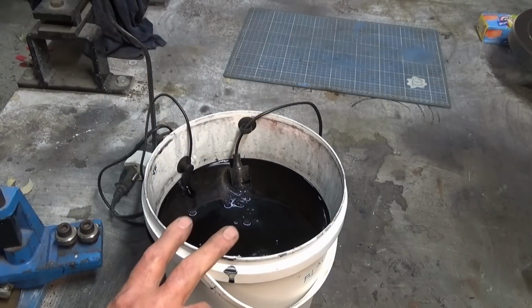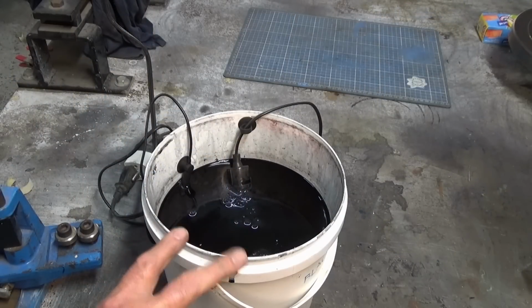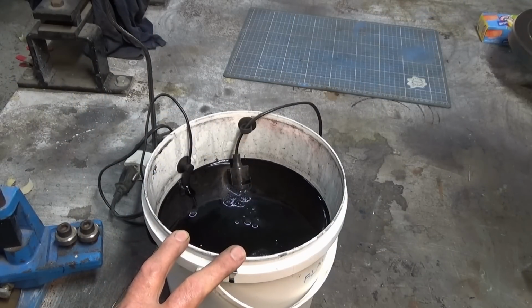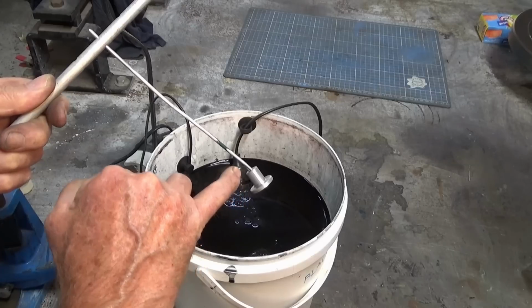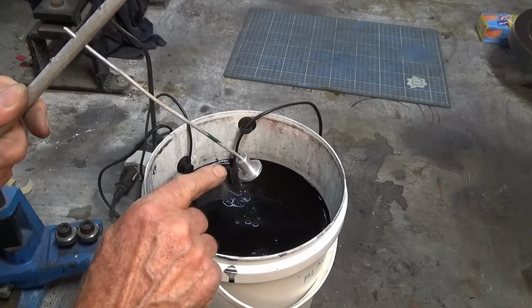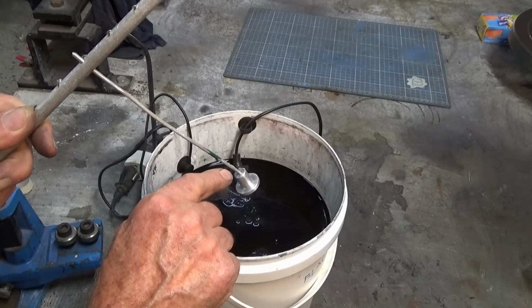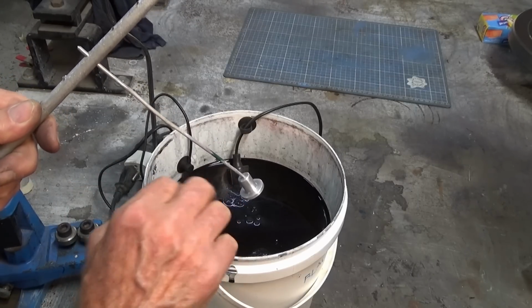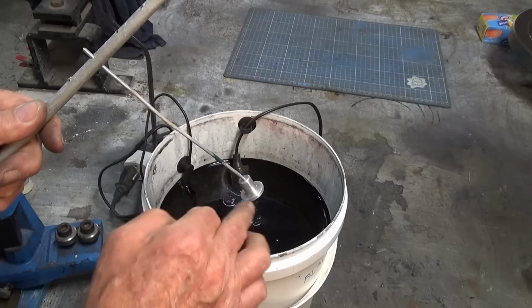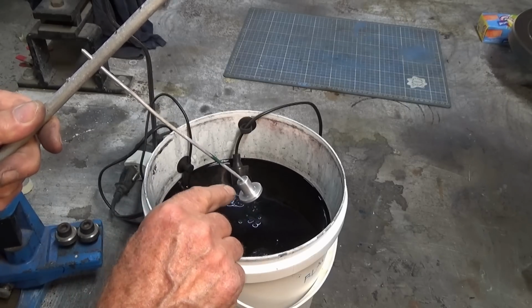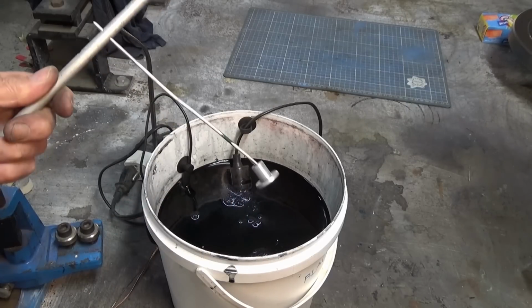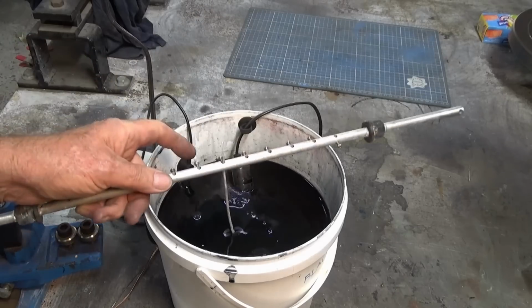Okay, I've got my black dye set up here, and I've heated this up to about 50 degrees centigrade, and we're about to dip the part, but I've been very, very careful about rinsing this. Often this threaded hole will hold a little bit of the acid from the anodising bath. If you don't rinse that out, it'll leach out of the hole and it won't dye in that area. So we'll try this now.